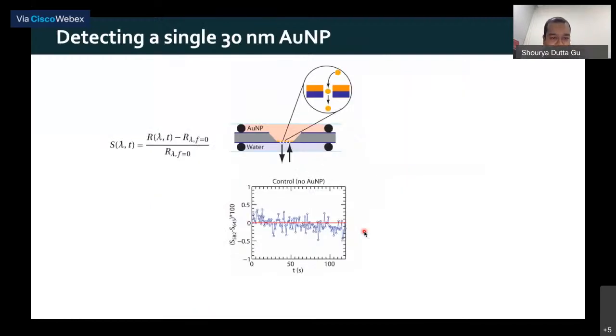Now, if you do the experiment, the experiment is very simple. You take the silicon nitride membrane, which is supported by the substrate. You put a well of water at the bottom and a container which contains the gold particles at the top. Naturally, the gold particles will diffuse from the top to the bottom. We would like to measure when these particles are diffusing, so you send light from the bottom and measure it in reflection to see the signal.